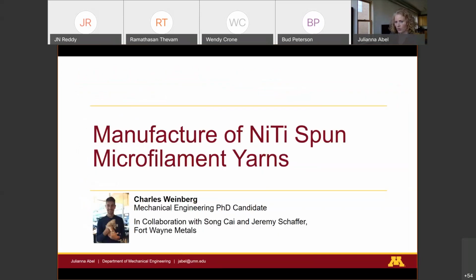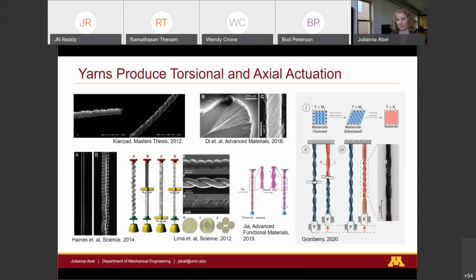So it's great, but you saw in that last image, the knitted area is not what we think of as a fabric. It was very much a textile, an open porous textile. And so we're looking to the next generation of these and how do we make these more wearable? And one way is to look at how we manufacture NiTi spun microfilament yarns. And so this is done in collaboration with a group from Fort Wayne Metals who are producing this material.